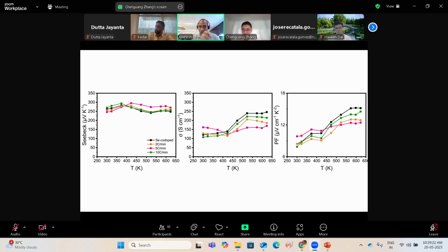With a slow cooling rate, the interfaces are decreasing. Nothing but cadmium is diffusing inside the matrix. Cadmium diffusing inside the matrix indicates the semiconductor nature might increase more. So the Seebeck increases and the electrical conductivity decreases. It's a good sign of cadmium diffusing inside the matrix.